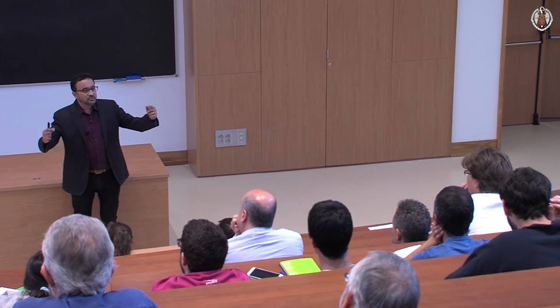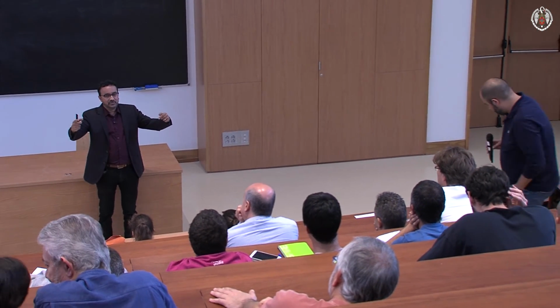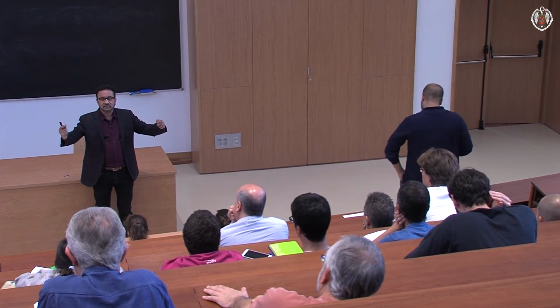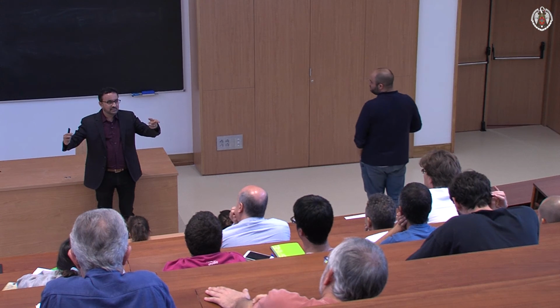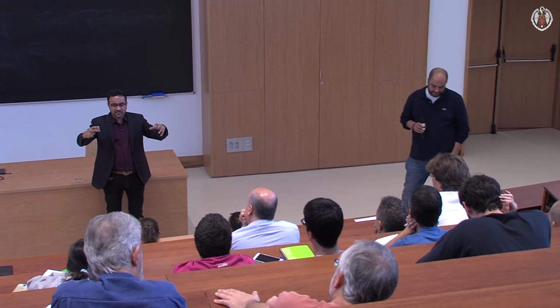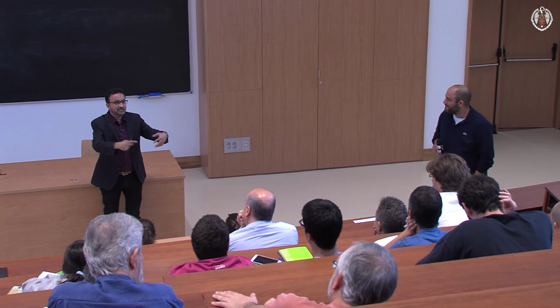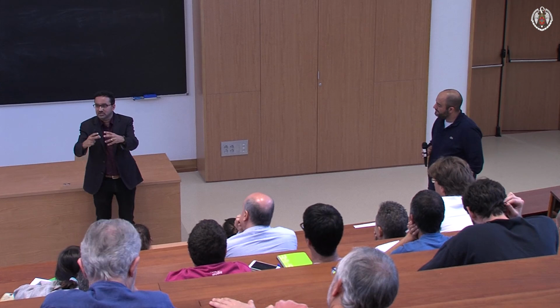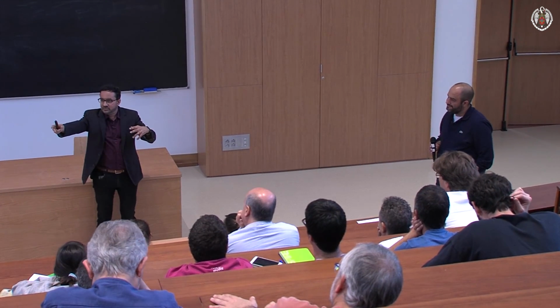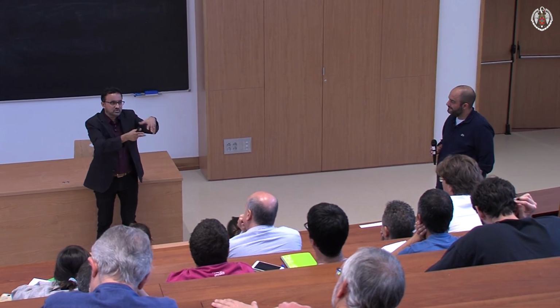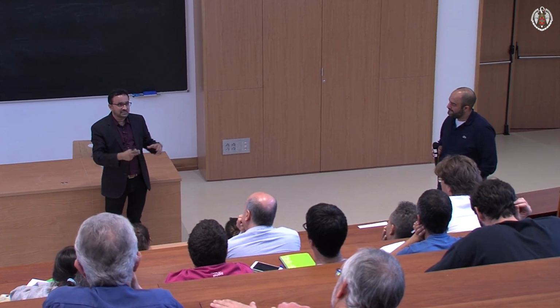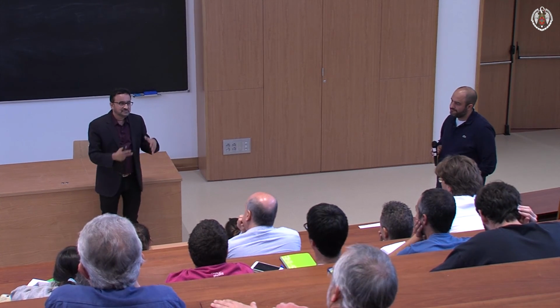By the way, you can also use a DC field, and people have done that. In fact, there's a group in Thessaloniki, Greece, that is trying something new. They're actually using DC fields on top of the AC fields, and this causes the heat to be focused. So this also leads to the previous question. There are ways of focusing it to specific areas even among the cells. You can use a DC field to focus the heating.